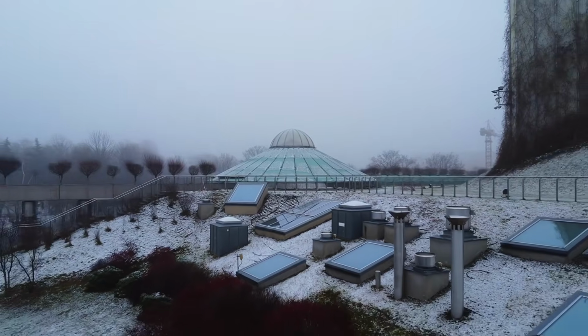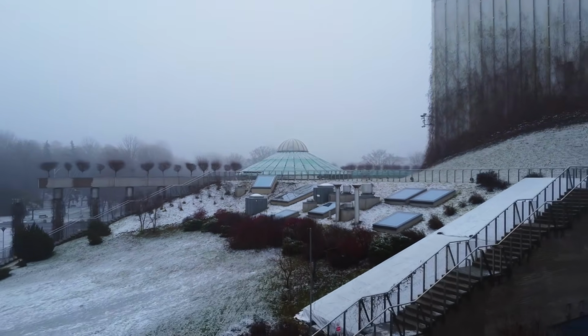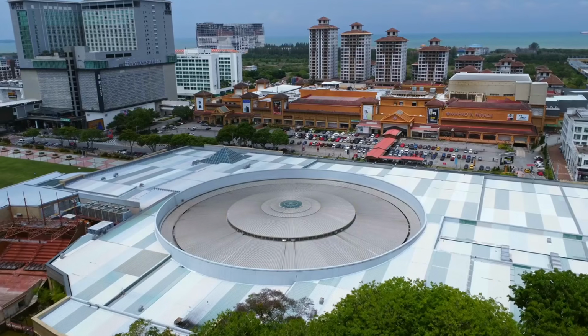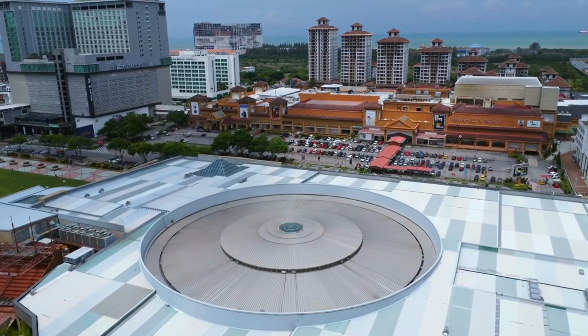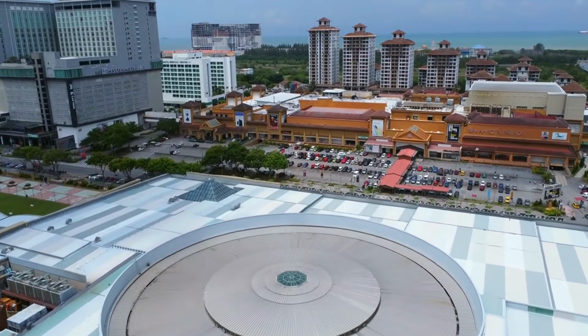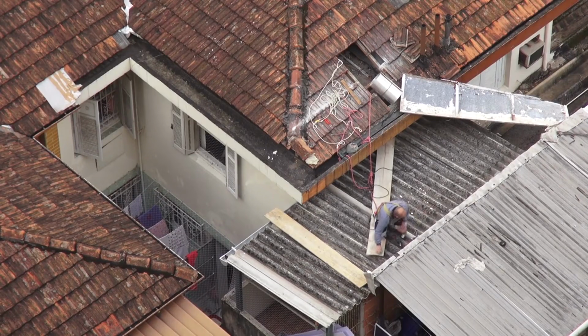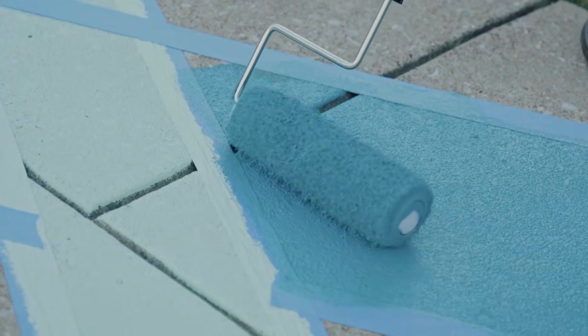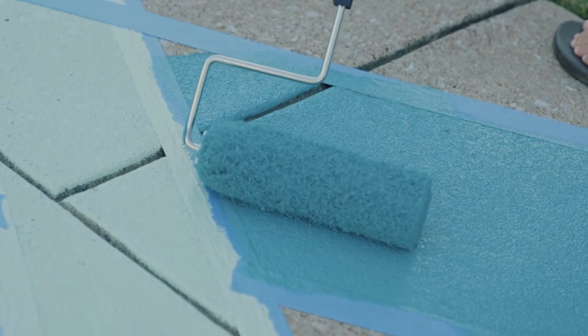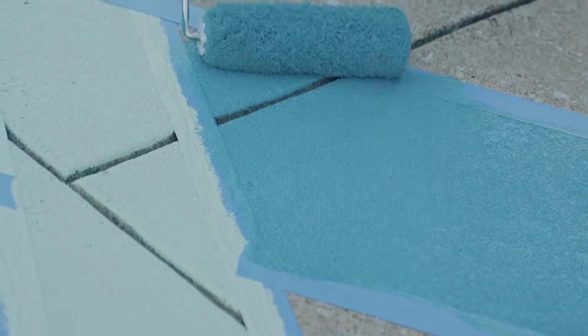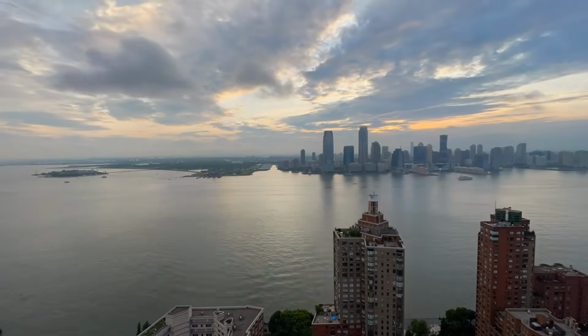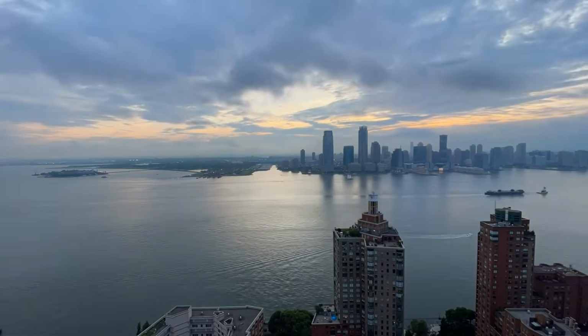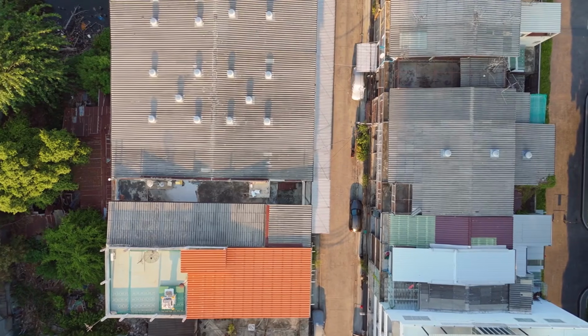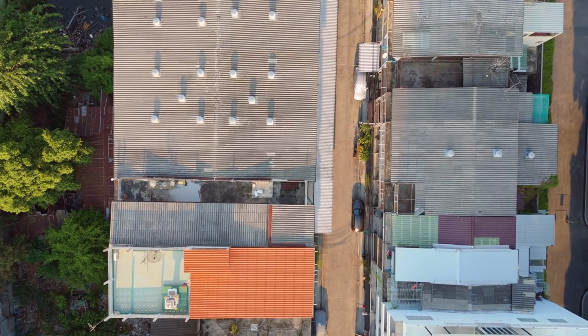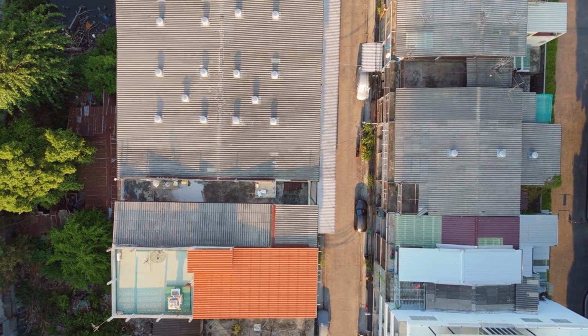There is one more modern innovation worth examining, which is cool roof coatings applied to existing asphalt shingles or low-slope membrane roofs. Elastomeric reflective coatings, the white roof movement popularized in New York City's CoolRoofs NYC program starting around 2009, can raise the SRI of an existing roof from single digits up to 75 to 85. Studies on New York City row houses showed a 14 to 23% reduction in cooling energy from white coating alone. This is the most accessible retrofit option for homeowners in climates where clay tile is unsuitable, available for $200 to $600 in materials for a 1,500 square foot flat roof area, and installable as a DIY project.